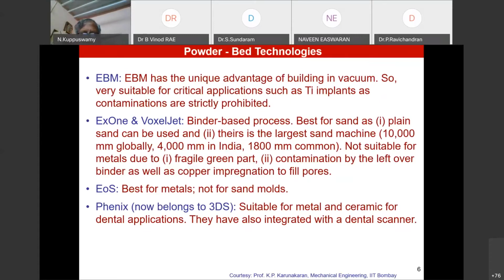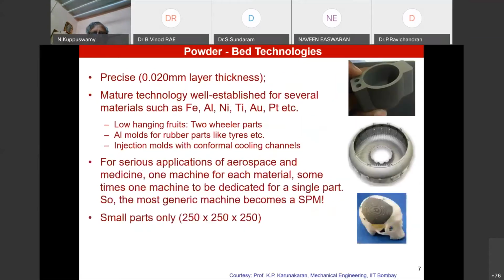Okay, then the next, the powder bed's major advantage for metal is you can control in a 20 micron thickness. It's possible. Of course, when you're trying to go into 20 microns, obviously a powder cannot be bigger than 20 microns. Then you're talking about powder in the 10 to 15 micron range. And you're also talking about a very, very high flow rate powder, such as a spherical powder with very little satellites, which flows well.